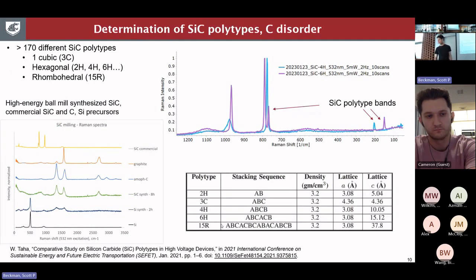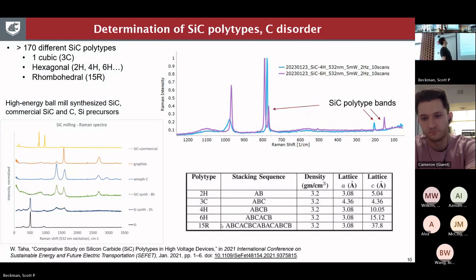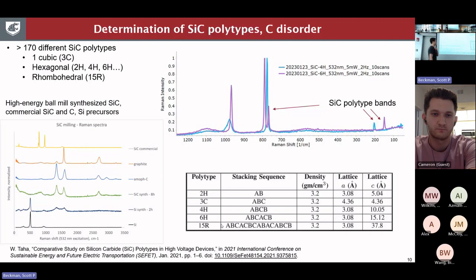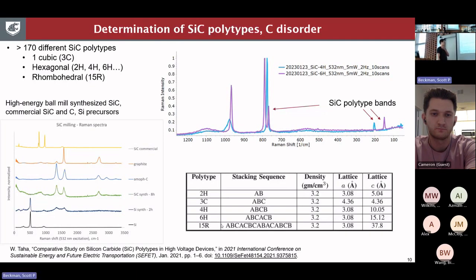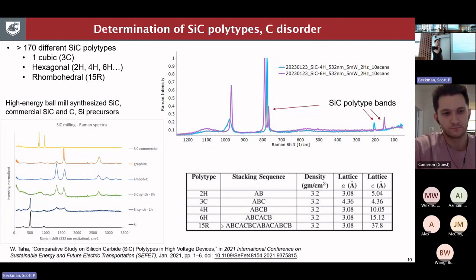We've also done a fair amount of work lately on carbon and silicon carbide using Raman. We can determine the polytype of silicon carbide — there are more than 170 different polytypes — by comparing mostly the low wavenumber peaks and also the band around 800 wavenumbers. For carbon samples, whether ordered, disordered, or some mix of amorphous — such as ball-milled silicon plus carbon, which is very disordered — there's a lot we can extract from the Raman spectra about the degree of order and disorder in carbon materials.